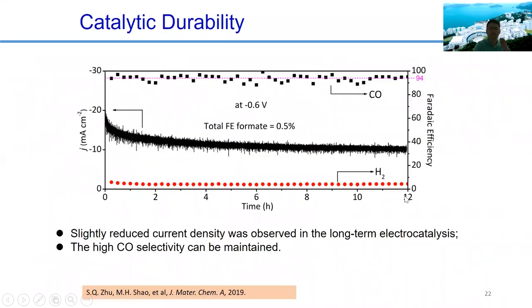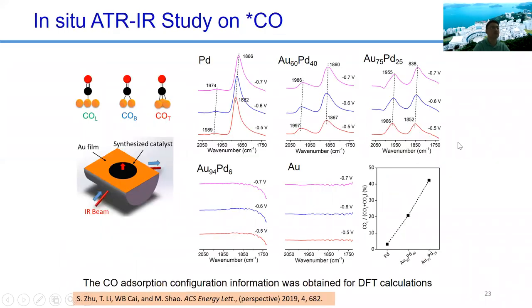And the durability. It's very important to test the long-term durability of the CO2 reduction catalyst, because in the past, due to the deposition of carbon on the surface, the long-term durability of most of the catalysts is very, very bad. So this catalyst is quite good. After 12 hours of testing, you can see that the current is quite stable, and the selectivity of CO is also quite stable.